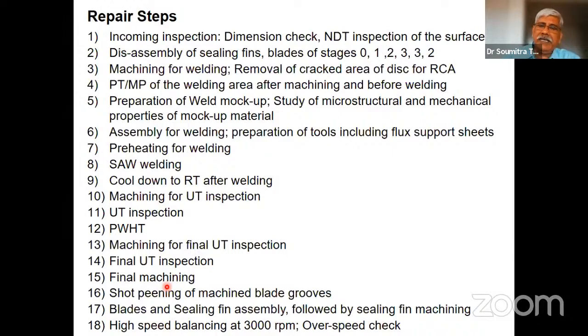And we had to do a fracture mechanics based calculation to see if that defect would grow with start and stop and how many start and stops it would survive, because we knew about the stress conditions in that location. So stress analysis was already done, so those data were available. And we found that that defect is not acceptable. Now, having done all this, you could not again take out and re-weld and reheat treat the material, because that would make the rest of the rotor too much deteriorated to be recovered. So it was decided that only a local repair, and you could not throw away the rotor, it was quite costly. So locally again, a repair and refurbishing was done.